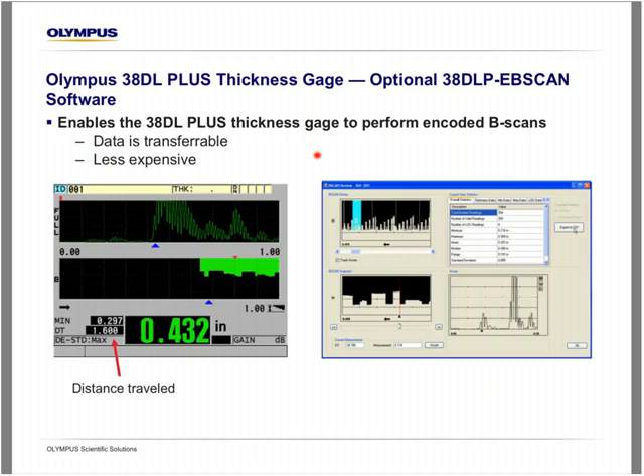So another application is encoded B-scan. The 38DL Plus and also the 45MG both come standard with non-encoded B-scan. Non-encoded B-scan just runs at a fixed rate and it doesn't capture the distance traveled. The encoded B-scan option for the 38 allows the 38 to be connected to a linear encoder and actually do encoded B-scans that capture thickness and also distance traveled. What's nice is these B-scans can be saved to the internal data logger and uploaded to GageView thickness, which you see here. Here's the whole scan. You can highlight a certain portion, do a more in-depth look, and adjust the cursor to see what the thickness is at that point.